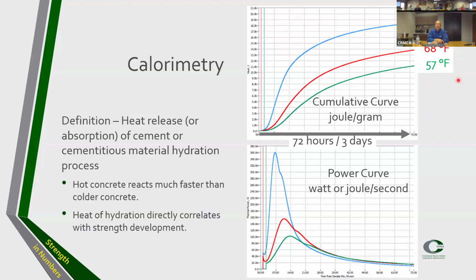And the heat of hydration from the calorimetry directly correlates with the strength development of cement. And we see in the lower graph, the power curve, it shows a differential that shows that the highest heat generation in this case is at about 7 hours for the 90 degree, and about 14 hours for the 57 Fahrenheit concrete. So again, the heat of hydration directly correlates with the strength development, and for us, it's a nice measure to see how a cement reacts at different temperatures. And also we can do that with admixtures to see admixture compatibility with different concretes.